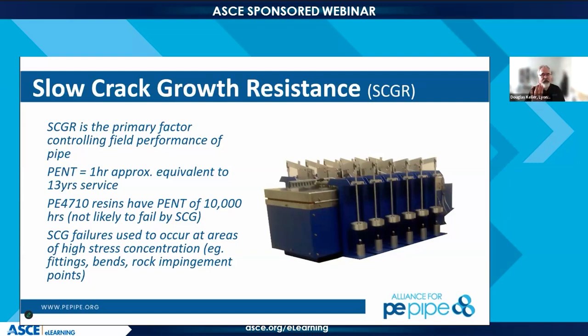Now hold on. When we developed the PENT test, a lot of work was done in exhuming pipe from the field. And it was determined that 1 hour of PENT resistance is equivalent to roughly 13 years of typical in-field service. The 4710 resins have to have a minimum of 500 hours of PENT. 500 times 13 is 6,500 years.